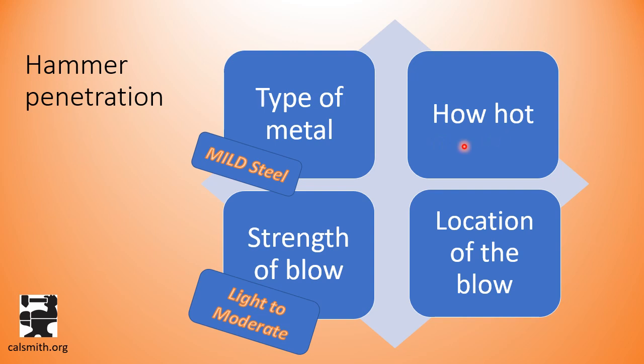The third factor is how hot you get your metal. Metal will weld in a range. You want to give yourself the best case possible, and that is to weld in the high end of the welding range, which is your bright orange to yellow heat.